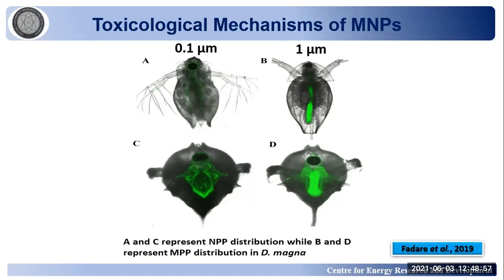But one of the things that we normally do in our lab before we use any of these products that we purchase is to first wash them. We wash them several times, centrifuging them. After we've washed them, we can be sure that the surfactants and also the preservatives that were added are no longer present before we administer the particles.